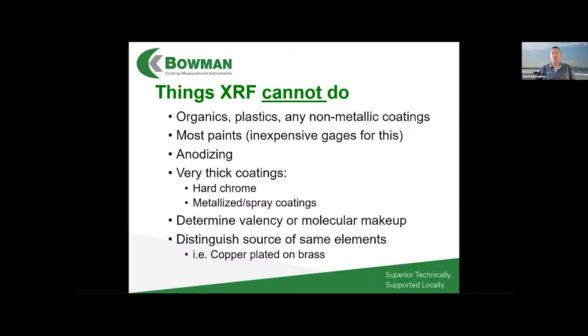Things XRF cannot do would be any of those elements that are lower than 13 on the periodic table. So any organic type coatings, plastic, non-metallic type coatings, paints. A lot of paints have a metallic component in there, a lot of times something like titanium or copper, something to help the color be more vibrant. We can sometimes do that, but there are inexpensive gauges. For a couple $100, you can get a gauge to measure paint thickness. So we don't really focus on that. Anodizing we cannot do, because that just forms an oxide layer on the aluminum. So that really doesn't change the elemental properties of the coating at all. So we can't do that.